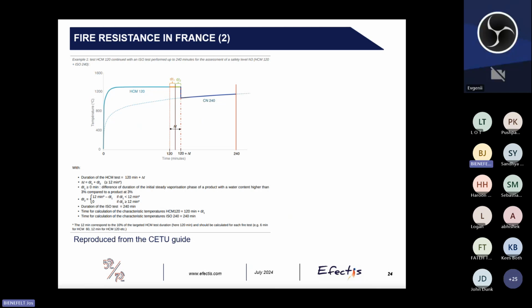So this is an example of the fire curve that's used in the CETU guide. Depending on the required safety level, different fire curves are used, or actually the lengths of the fire curves differ. For the most severe case, the safety level N3 case, you will have a fire curve of 240 minutes, of which the first 120 minutes are the HCM 120 fire curve. And then after 120 minutes, it will pick up at the standard fire curve, the CN 240 part. And between those curves, there's an area to cross over from one curve to the other.